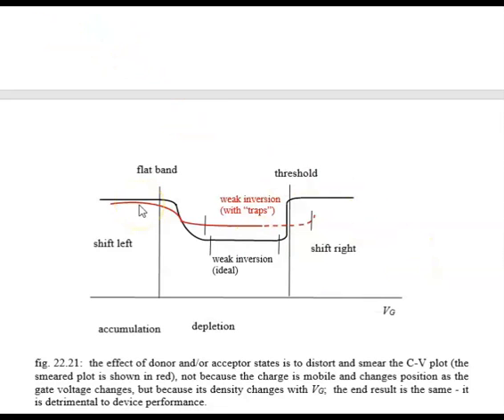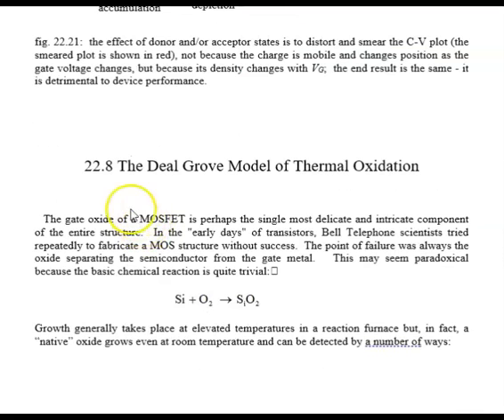So let's at least start our discussion on the actual growth. How do we make this oxide? We're going to be looking at the Deal-Grove model of thermal oxidation. And the chemical reaction at the silicon interface is pretty easy. You just have your silicon. It's in oxygen. It's in air. It could be air at room temperature even.